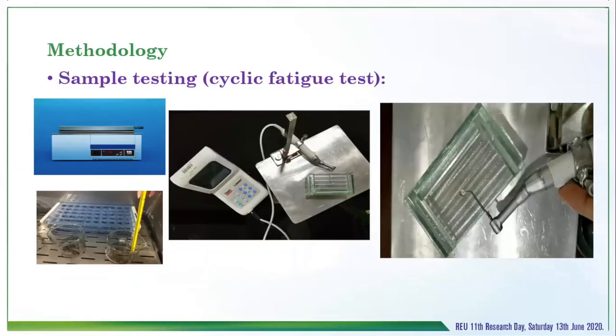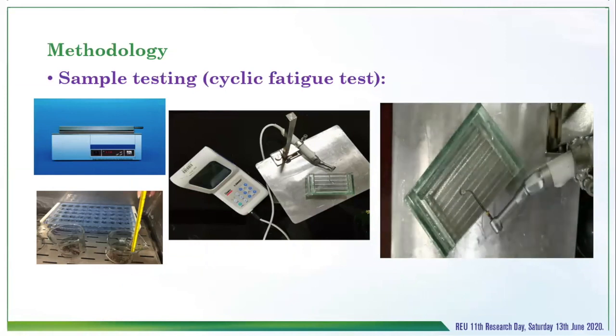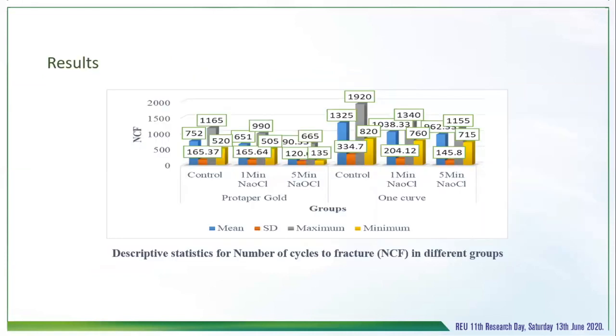The methodology: after the preparations, cyclic fatigue for all the instruments was tested under continuous clockwise rotation according to the manufacturer's instructions. The time was video recorded until instrument fracture was observed. So the results: descriptive statistics of the number of cycles to fracture in the different groups show a significant difference between the 2 groups, the One Curve group and the Protaper Gold group.